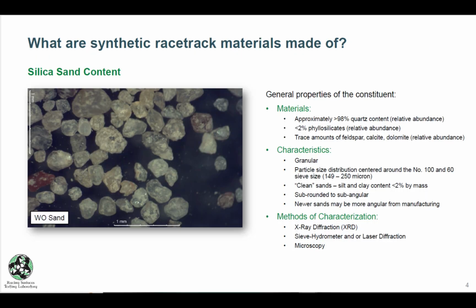One of the most important features of a synthetic track is the sand content. We're looking for high quartz content. We can test to see if the racetrack has the high quartz content. We're looking for low phyllosilicates, that's going to be your clay content, and we only want to see trace amounts of other types of minerals.